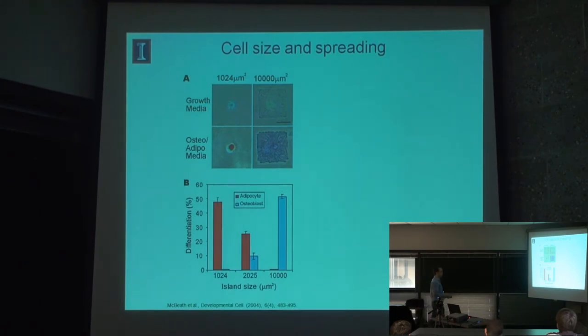I think a lot of the initial argument was that clearly there's a paracrine signaling mechanism where biological signals are diffusing across the dish. But what Chris Chen and now others have done is they used micropatterning to culture cells either in small islands, where they remained as big balls sitting on the surface with very low cytoskeletal tension, or on large micro islands patterned on glass, such that they can spread out and get a high degree of cytoskeletal tension. And then they mixed two medias together, one that promotes fat and one that promotes bone. After about a week in culture, they stained them for lipid droplets, shown in red, and they show that cells in the small islands almost exclusively turn into fat, while cells in the large islands that are well spread almost exclusively turn into bone.